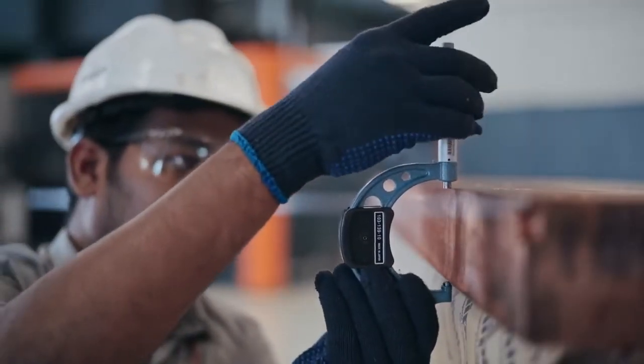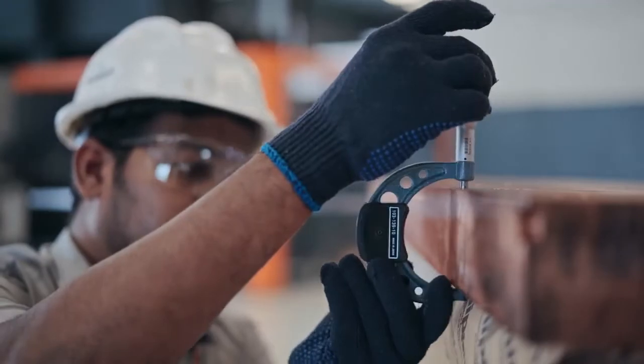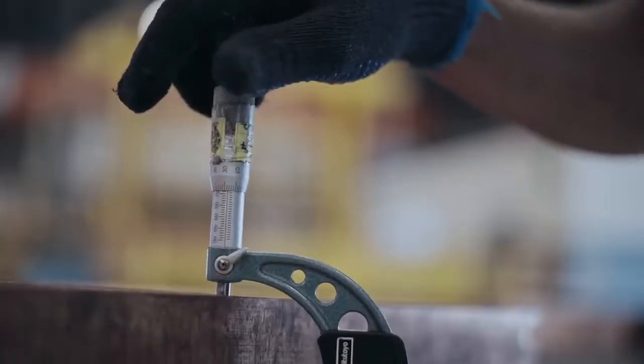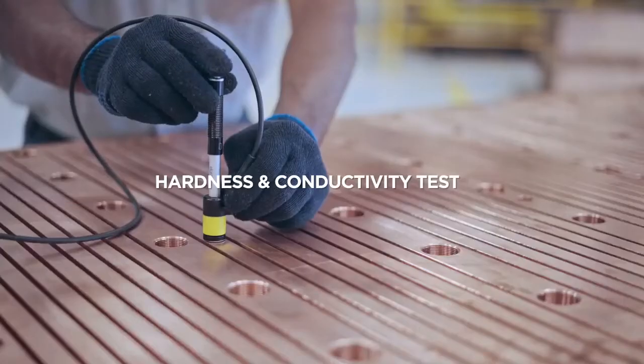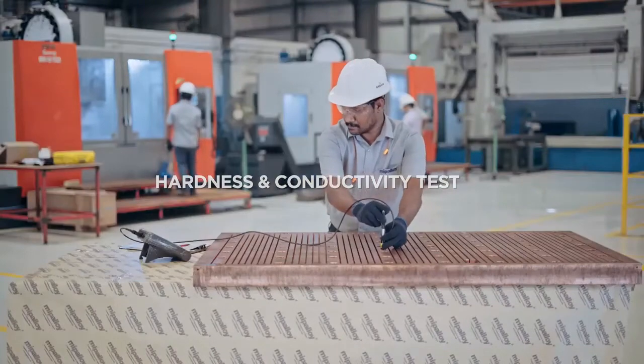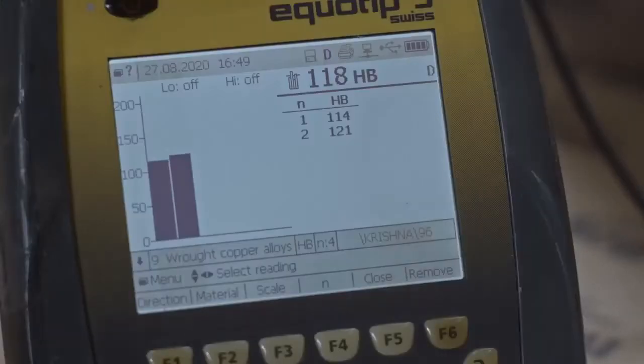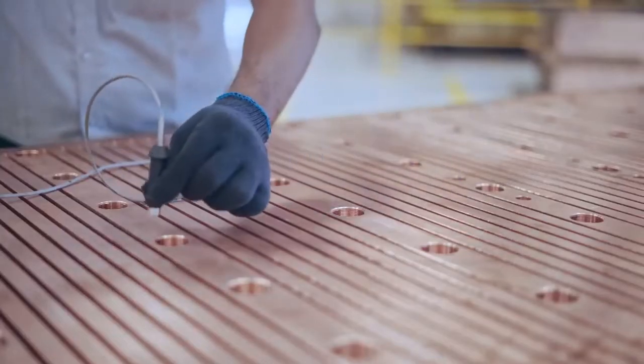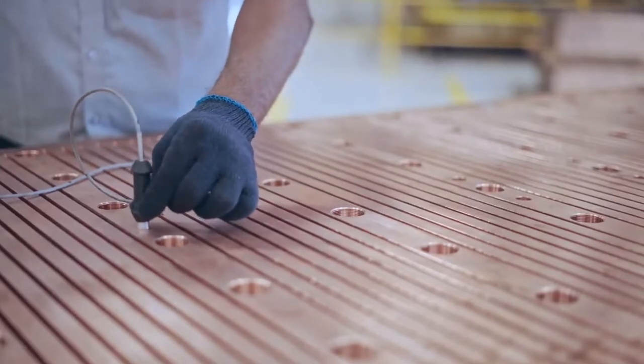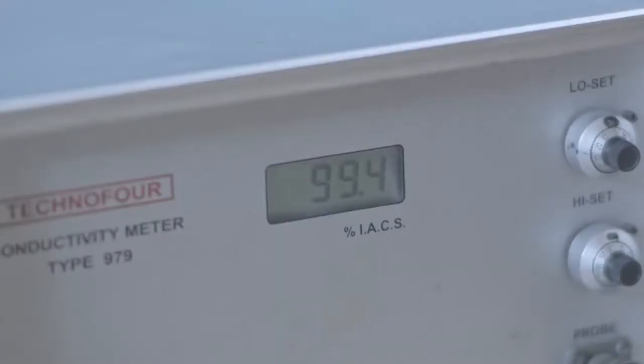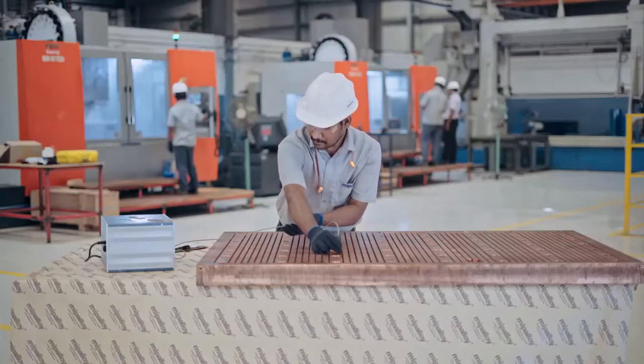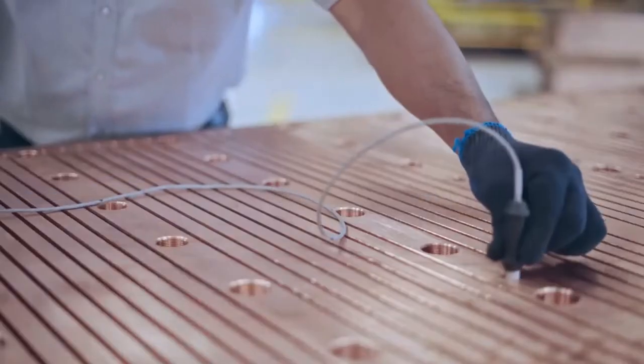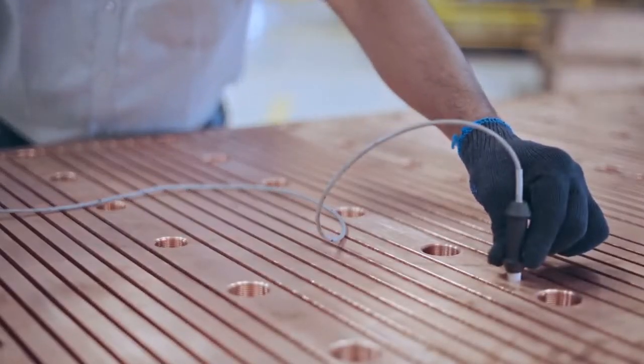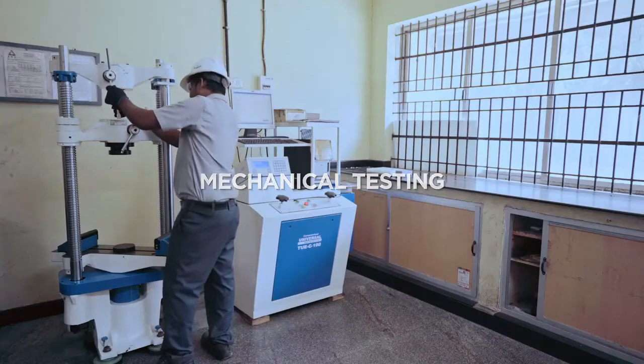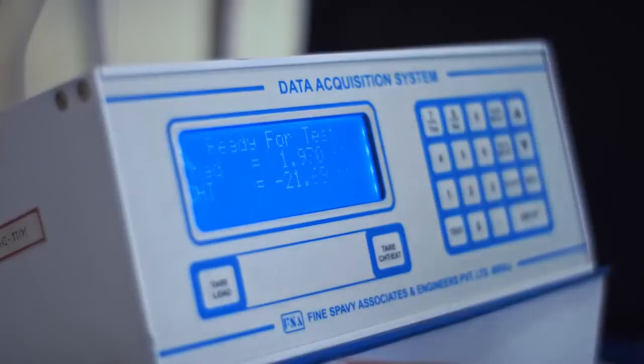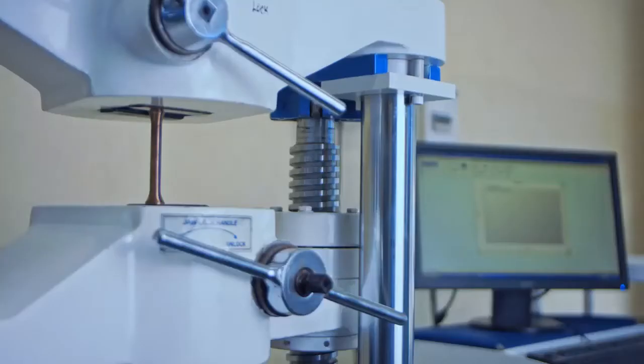All our instruments and testing equipment are calibrated periodically as per ISO norms. We have both stationary and portable hardness testers. Our portable conductivity meter can measure the electrical conductivity at multiple positions of the mold plate with an accuracy of 0.1% IACS. It is critical for mold plates to meet the required mechanical properties in order to give good performance